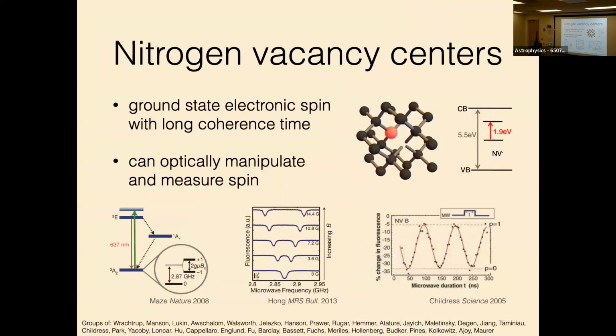Okay, so on the quantum sensing side, what we're mostly focused on is the nitrogen vacancy center in diamond. This is a color center in diamond that you get by taking a diamond lattice, taking out 2 carbon atoms, and then putting 1 nitrogen back in, so that you have the substitutional defect next to this vacancy in the lattice. The reason that this is a really interesting defect is that if you look at the electronic states associated with the NV center relative to the conduction and valence band edges for diamond, you really get this mid-gap state. And then diamond has a large enough band gap that you have enough headroom that you can even have orbital excited states that are still very, very deep mid-gap states.